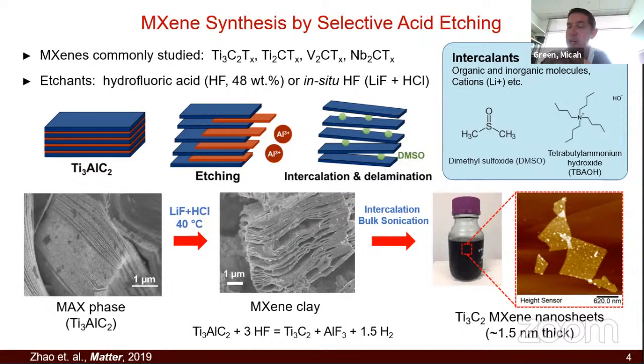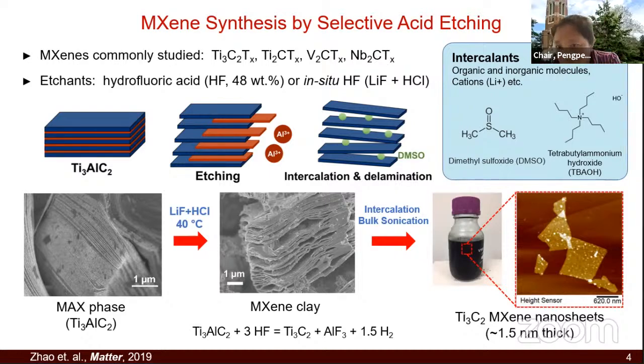We're somewhat limited on how much we can change the surface functionality because for us, we need it to be dispersible in water for several reasons. But one of the reasons we have to disperse it in water is it makes it really easy to separate your MXenes from your parent material. You never get 100% yield, so you have to separate the MAX from the nanosheets. So anyway, there's a lot of research still going on in that area, trying to change the functional groups.